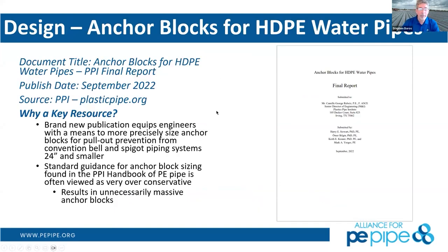So another thing we see a lot about is blocking, anchor blocking, and how do you restrain polyethylene pipe? First of all, know that it's very easy to restrain polyethylene pipe because it has a lower modulus than other materials. The resulting force from any type of thermal cycling event or soil movement, the amount of force generated by the polyethylene is going to be much, much smaller than it will be for that same event on a metallic pipe such as ductile iron or even PVC. So you have to look at it individually.